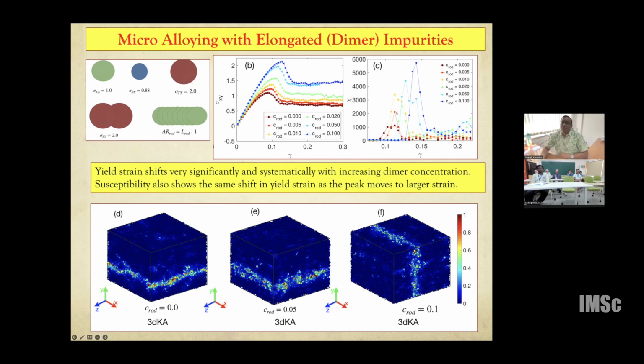And if we compute the susceptibility, it turns out the susceptibility peak increases very rapidly with increasing dimer concentration. So that is signaling some sort of shear band formation. And indeed, when we look at the spatial map in terms of this non-affine displacement, we see that already in the samples, you start to have some shear band. But the major achievement in these dimer simulations was that the yield point would be shifted by a significant amount.